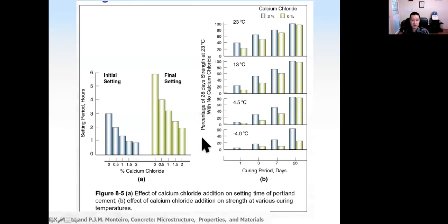But this figure shows us how calcium chloride can change the setting time. This is the increased dosage of calcium chloride. The initial setting time and the final set time both reduce.